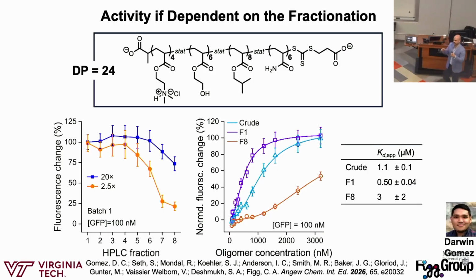This is saying that even though as an ensemble we're getting increases, there are preferential binders within that single polymerization, and we can actually isolate them and characterize them. This is really cool because this is equivalence to GFP. Essentially, if our GFP is at 100 nanomolar, we can add in 250 nanomolar of our random heteroligomers, and we get essentially fluorescent saturation for a lot of these signals. That's a pretty low equivalence of binder to protein where they're not sequence defined, and we have different compositions. Even though we enrich them, we're still getting pretty strong binding just by the composition of monomers that we added.